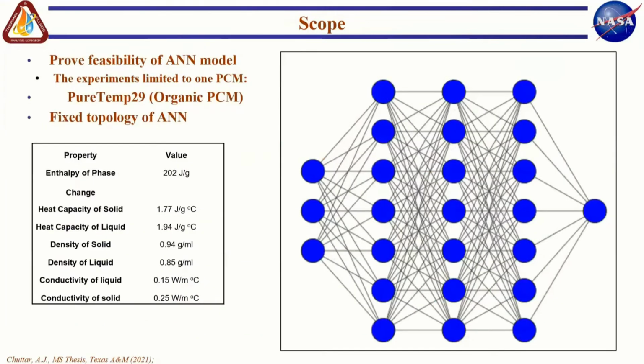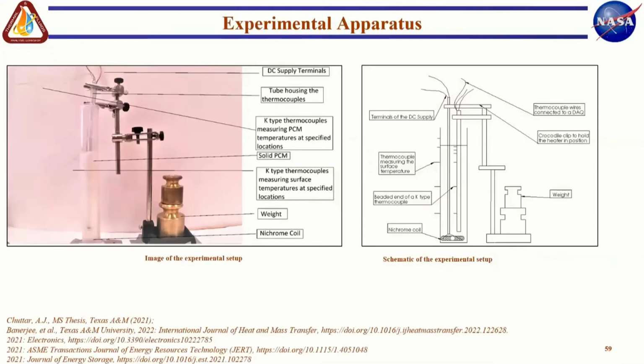So we used PureTemp 29, which is an organic PCM. We used a fixed topology artificial neural network configuration just to prove the feasibility of this concept, and also to compare the performance of the machine learning algorithm when you are eavesdropping by measuring the surface temperature compared to the actual temperature of the PCM.